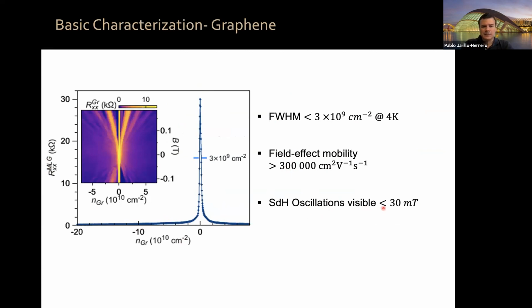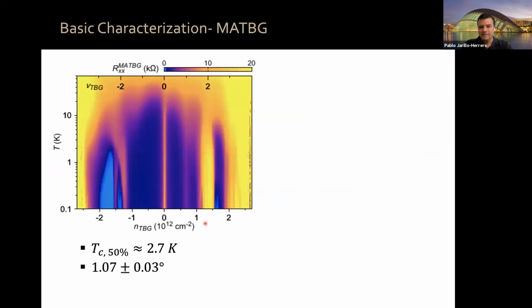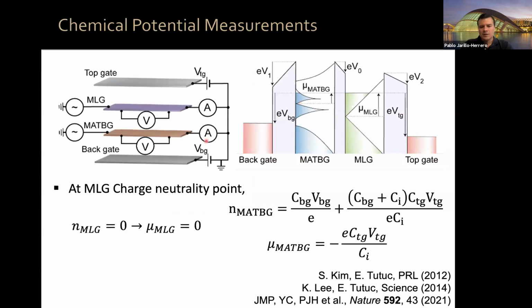Now, this is the resistivity as a function of density in the magic angle graphene as a function of temperature. You can see charge neutrality, something happening at filling factor 1, filling factor 2, filling factor 3, superconducting domes, all of the beautiful things that I showed you before. This is a device with a pretty high Tc, 2.7 Kelvin. So let's check that this chemical potential measurement story works. For that, I'm giving you here this equation now. If you track the monolayer graphene charge neutrality, so if you make sure, through the combination of top gate and back gate, that the monolayer graphene is at charge neutrality, zero density.